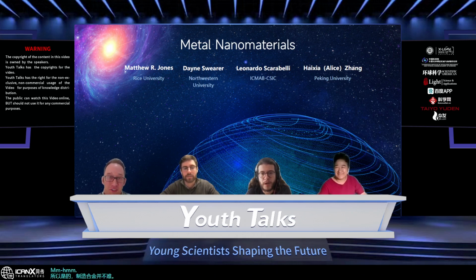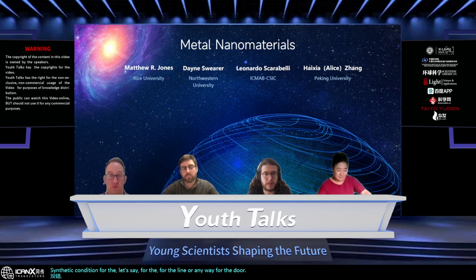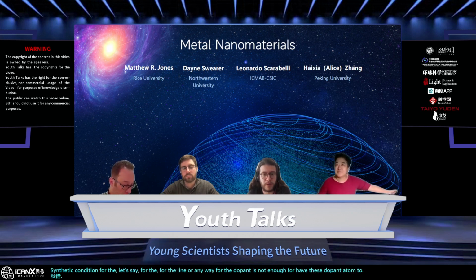Mm-hmm. Yeah, exactly. And in your case, I think that your synthetic condition for the alloying, or anyway for the dopant, is not enough for these dopant atoms to migrate within the crystal. Like you're assuming that you always have them on the surface, correct?